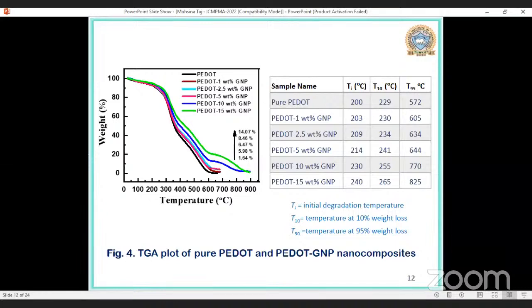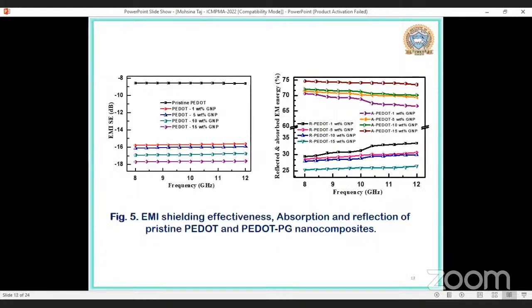They have reduced degradation of the polymer has decreased with the addition of graphene nanoplatelets. We have studied the electromagnetic interference shielding properties of the prepared samples in the 8 to 12 gigahertz frequency range, that is in the X-band range. We have observed that as we increase the concentration of graphene, the electromagnetic interference shielding effectiveness has increased. As we increase the concentration of graphene, a conducting network will be formed inside the composite, and also the interaction between the conducting filler graphene and the incident electromagnetic radiation has resulted in the enhanced electromagnetic shielding effectiveness.